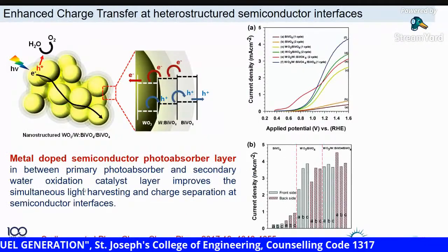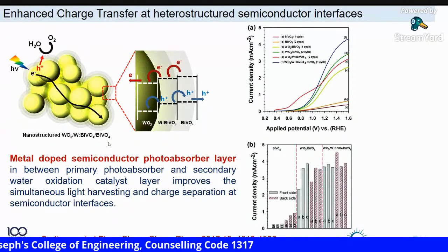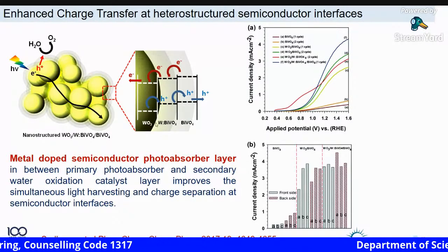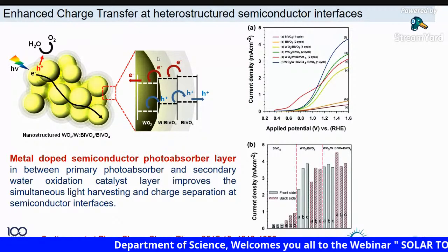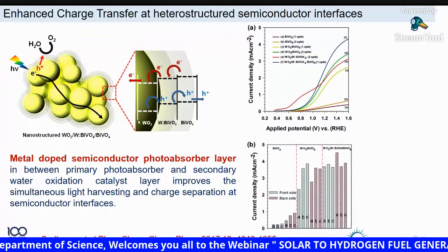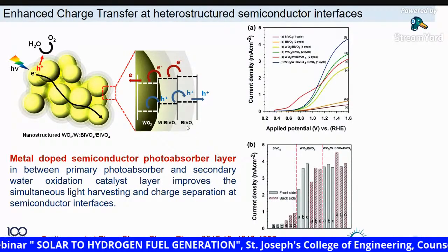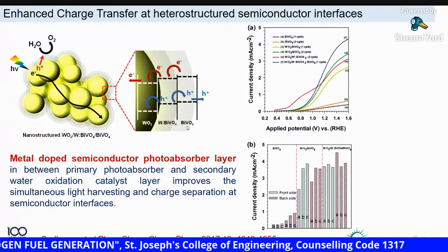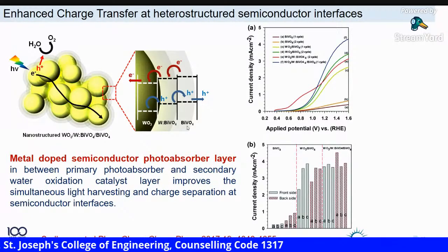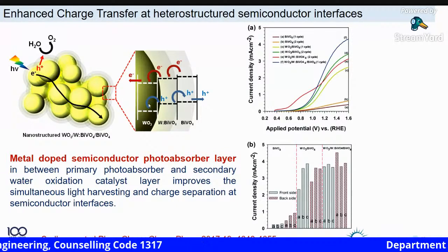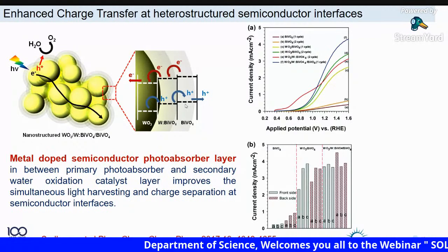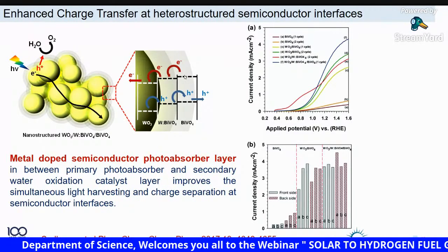Then in another report, we introduced an interfacial charge separation layer between the primary semiconductor and secondary semiconductor. It's like a sandwich layer. So tungsten oxide bismuth vanadate is one of the best sandwich heterostructures in the photoanode area these days. But still there are surface states existing in between the WO3 and bismuth vanadate. It may affect the charge transfer injection from the secondary layer to the primary layer.